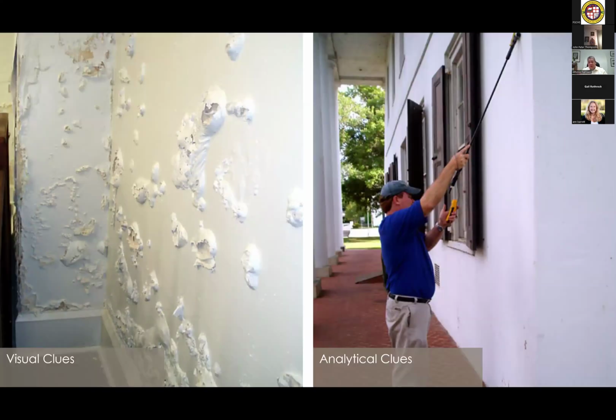We might use, on the right-hand side, that's a moisture meter, an electronic moisture meter that we're running up and down to figure out where is the changeover from wet to dry. And in this case, it's about 14 feet up the wall, which is exceedingly unusual. And we also look for visual clues, such as on the left-hand image, where you see areas where the moisture has clearly gone up to the interior, and they've made an ill-advised attempt to put on an elastomeric paint, a plasticky paint, to try and keep the water in the wall. And that's failing, of course.